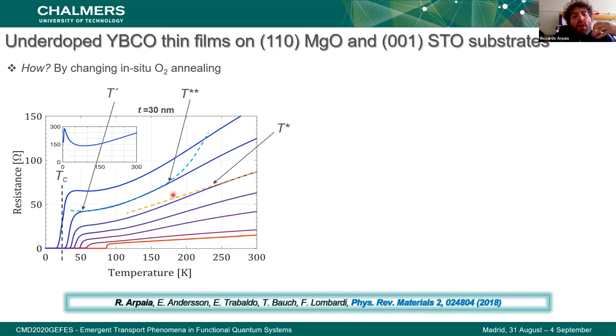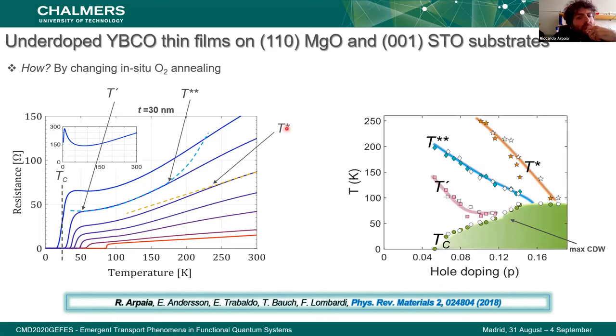And from this temperature, from this behavior, we can extract different temperatures, the pseudogap temperature and others. And then we plot these temperatures as a function of the doping of the film. And amazingly enough, what we see is the phase diagram, which is in perfect agreement with those of a single crystal. And in particular, I want to highlight here that we see also the depression of the superconducting phase diagram, which is a strong hint of the presence of charge density wave in the system that we are studying, even if these are thin films.